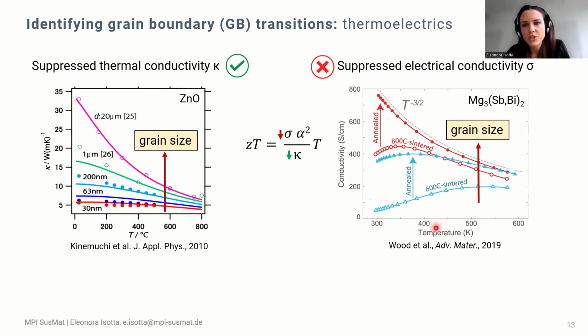But at the same time, having a small grain size is typically associated with a reduction in electrical conductivity. Typically, in the case of electrically resistive grain boundaries, one observes a temperature-activated behavior. Small grain size samples show a much lower electrical conductivity at low temperature compared to high temperature, where the idea is that charge carriers, with increasing temperature, are able more and more to overcome the potential barrier at the boundary. So this is the general expectation when we have a variation in grain size.